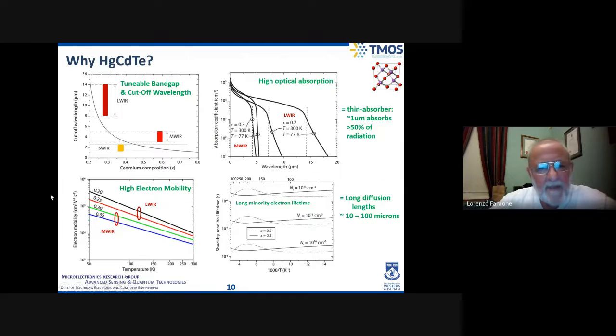But basically, mercury cadmium telluride can cover all of those wavelength bands. And so this sort of says why mercury cadmium telluride is essentially the material of choice for ultra high performance. You can see by changing the cadmium composition in the alloy, I can tune the cutoff wavelength anywhere from the shortwave infrared into the midwave infrared out into the longwave infrared.